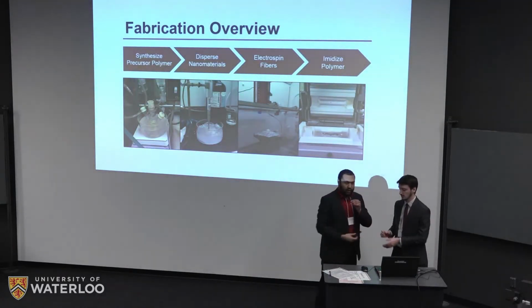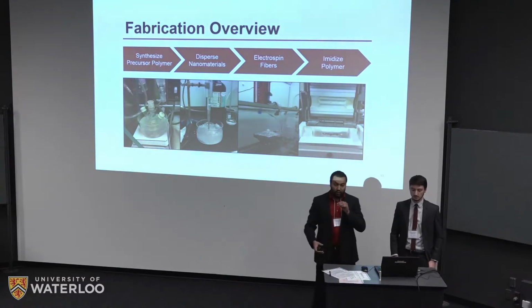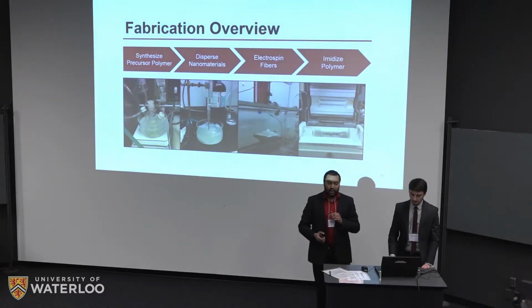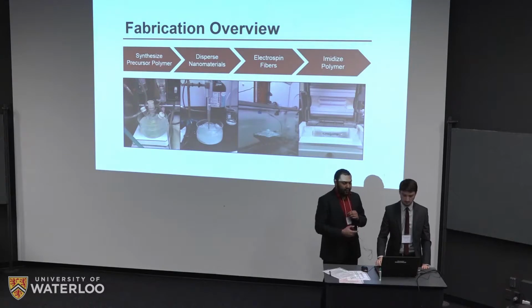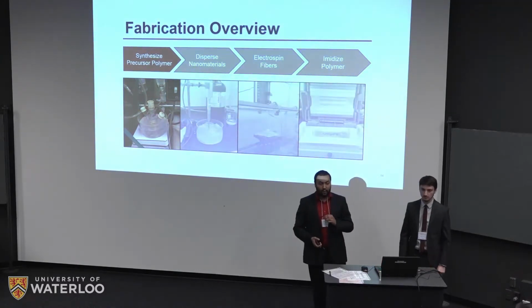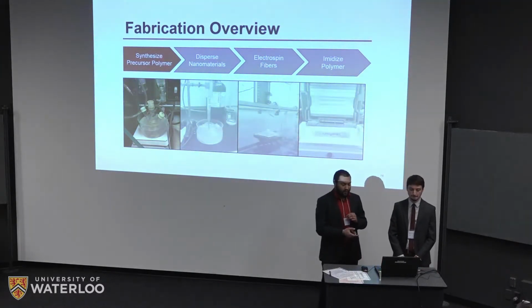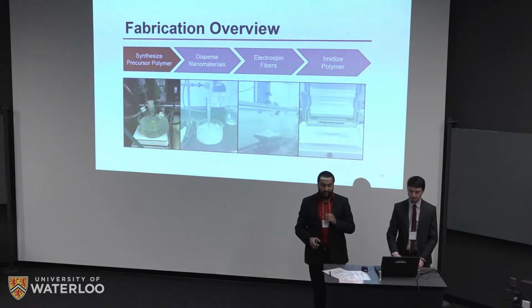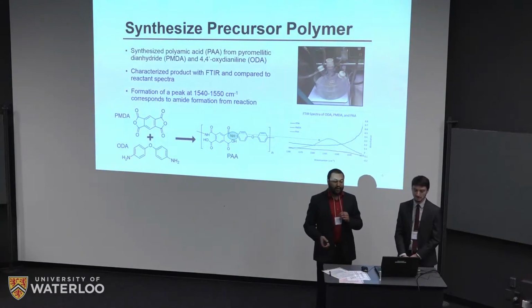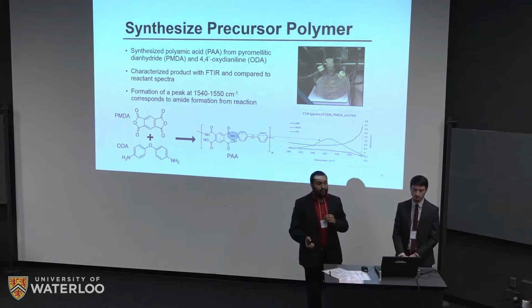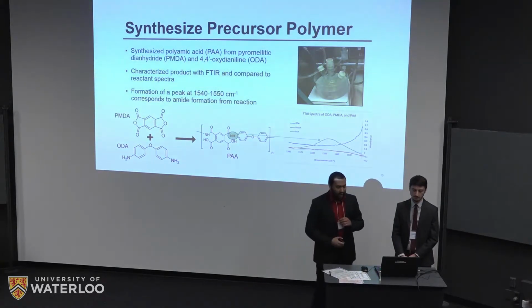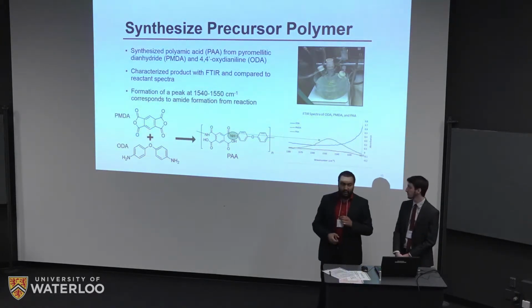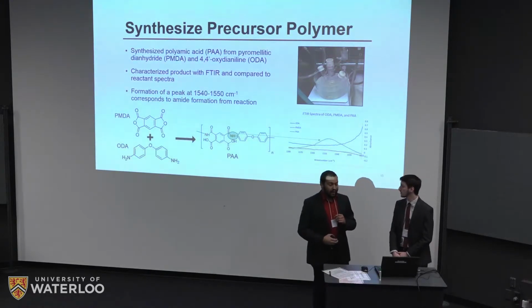So now we're going to go through a quick fabrication overview of how we made our polyimide from start to finish. The first thing that we had to do was synthesize a precursor polymer. This polymer is called polyamic acid, and it's made up of pyromellitic dianhydride, PMDA, and 4,4-oxydianiline, ODA. You see on the slide here, this is a simple polycondensation reaction that we ran in DMF.